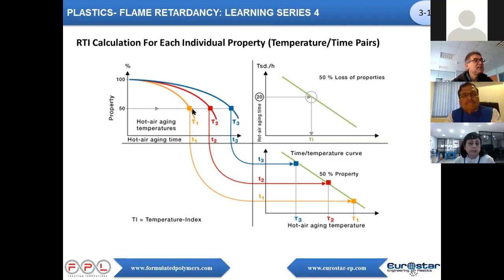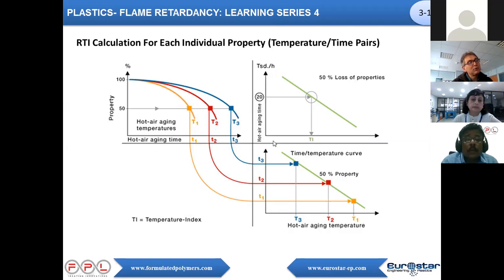So you have, for example, T1 is the time for 50% mechanical properties retention at 200 degrees C. Then you increase the temperature by 20 to 30 degrees. Do the same exercise, you have an average temperature for the half of life and a third temperature. Then you plot on this chart the time temperature relation, and you draw a curve of half of life properties. So you have a regression curve, and it is extrapolated to 60,000 hours at UL, and it's the value you can find on the yellow card.